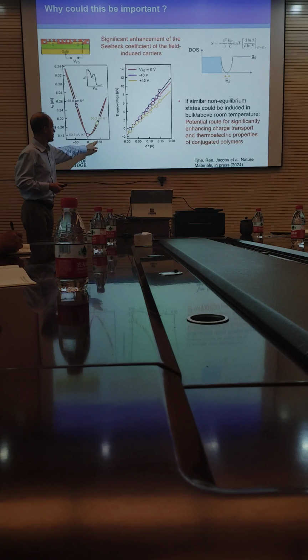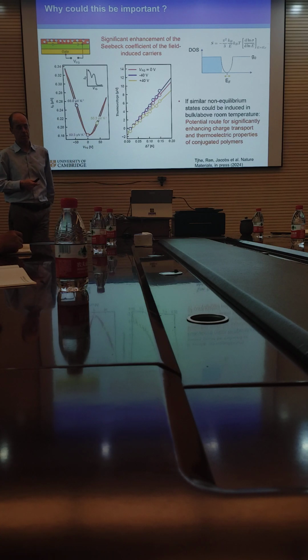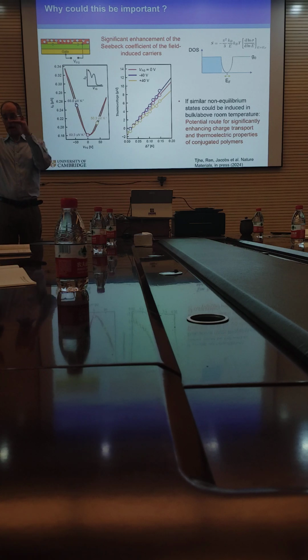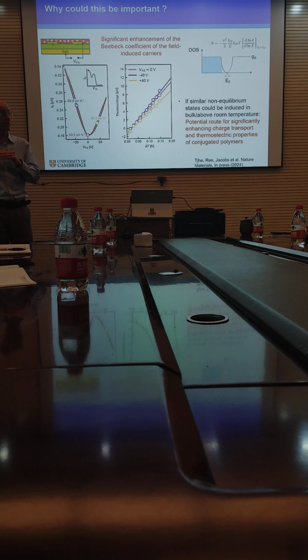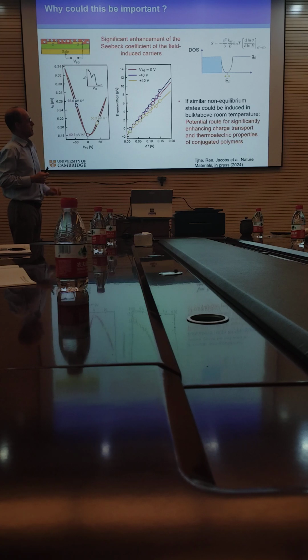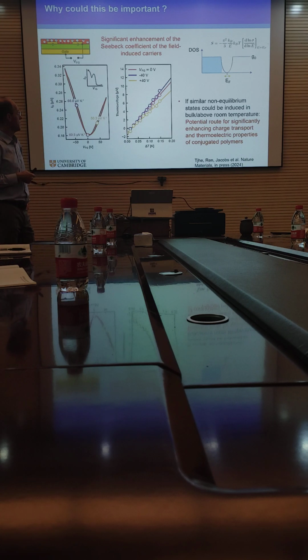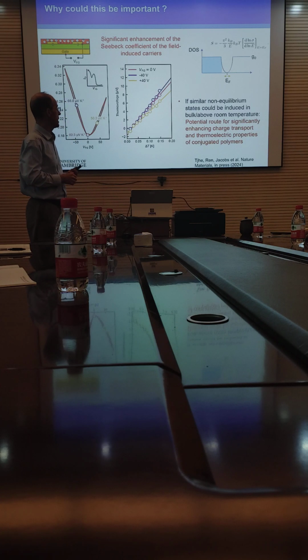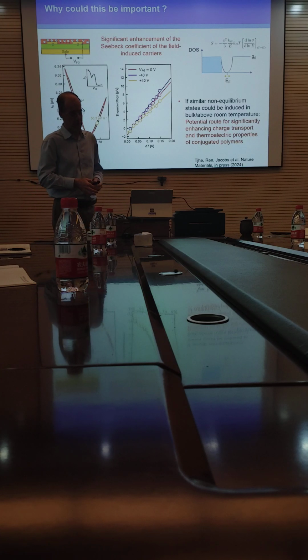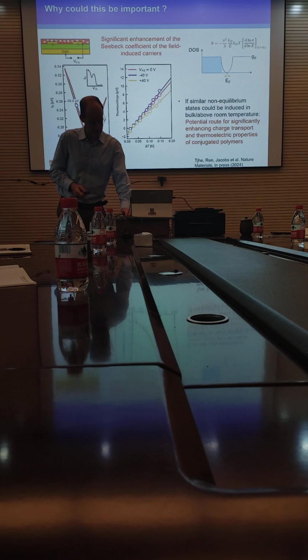If we go in the other direction, the Seebeck coefficient actually goes down. It goes down to 50 microvolts per Kelvin. That's because the bulk is p-type, the interface becomes n-type, and the n-type has a negative Seebeck coefficient while the bulk has a positive Seebeck coefficient, and they cancel each other to some extent. So that makes sense. We think that if we were able to do this in the bulk, at the moment we are only able to do this at the interface, if we could add these extra charges in the bulk as well, this might potentially provide a route for significantly enhancing the Seebeck coefficient of conjugated polymers. So that's something we are exploring at the moment, whether it is possible to do something similar in the bulk.